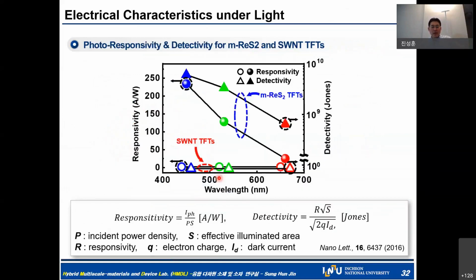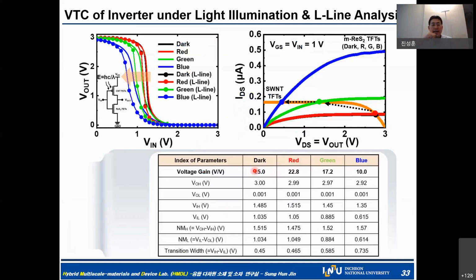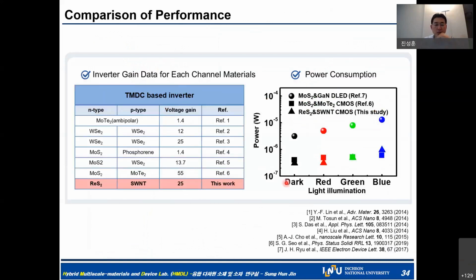With this kind of approach, we entirely explored the photo responsivity to all the wavelengths. So we achieved very wonderful properties in terms of photo responsivity and detectivity. The next thing is we also checked the entire voltage transfer characteristics under light illumination, and load line analysis has been performed here. With different wavelengths, red, green and blue, we achieved entirely different voltage gain and wavelength dependent transfer characteristics here. With this kind of data, we achieve the entire power level according to different wavelengths.